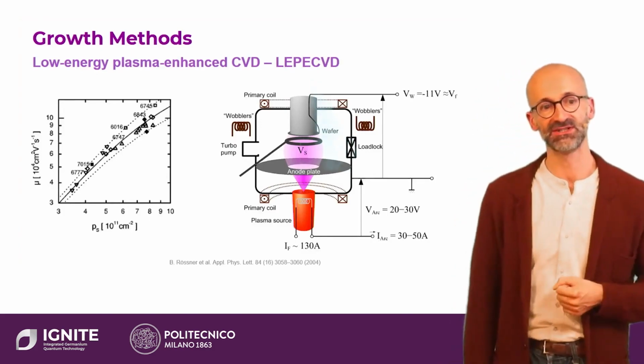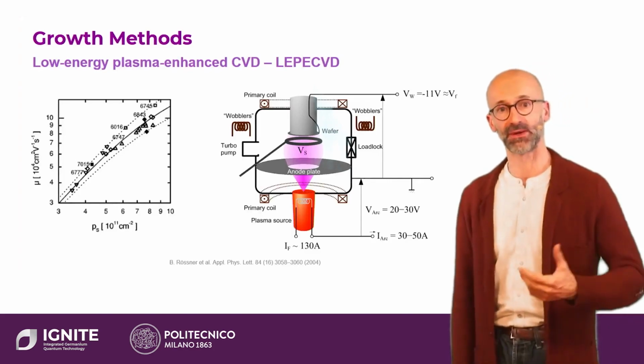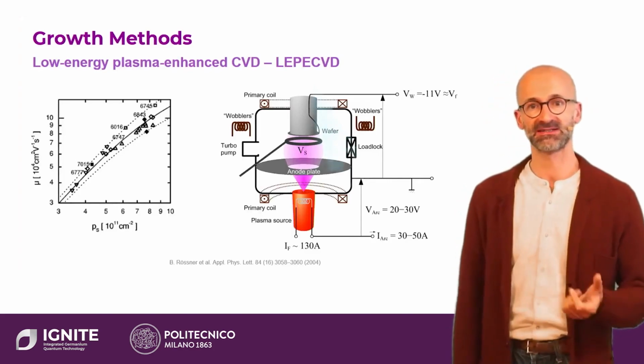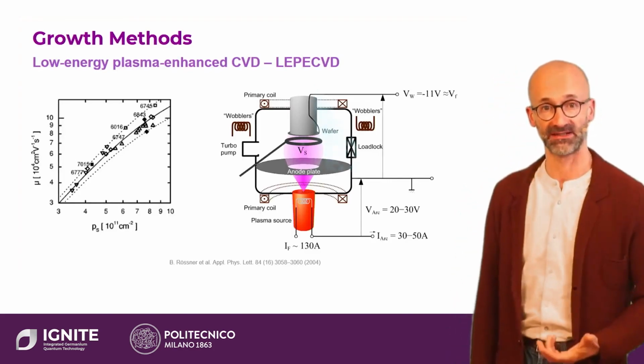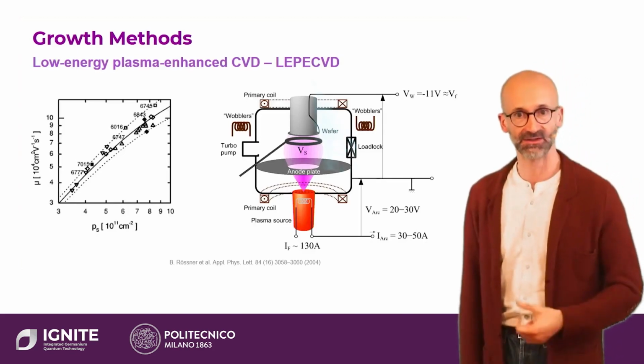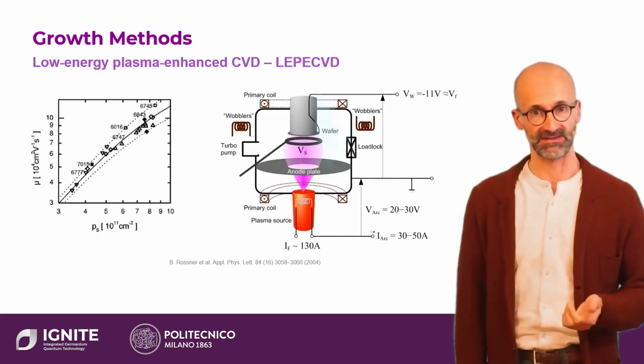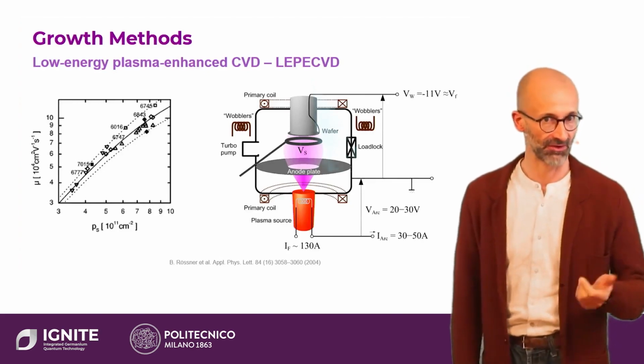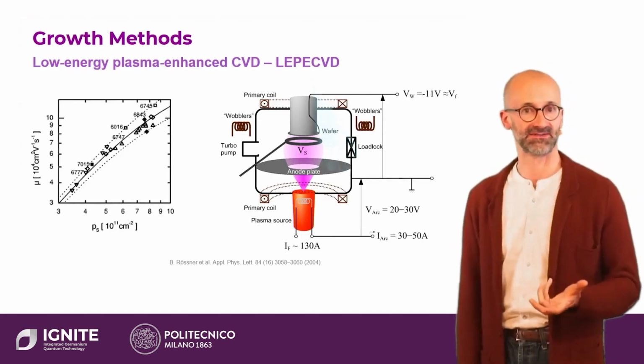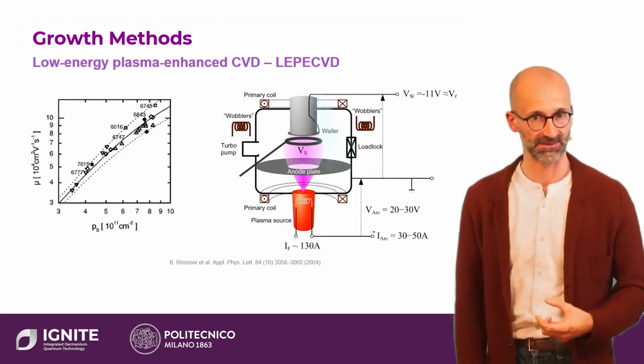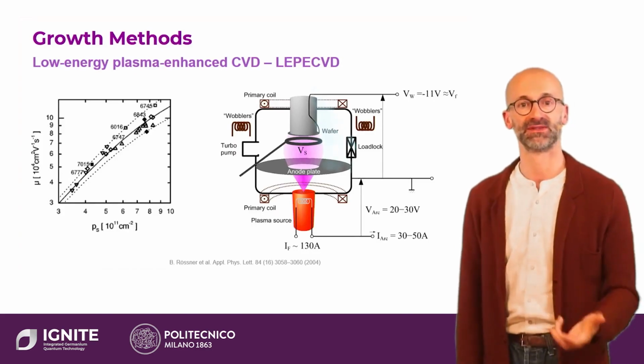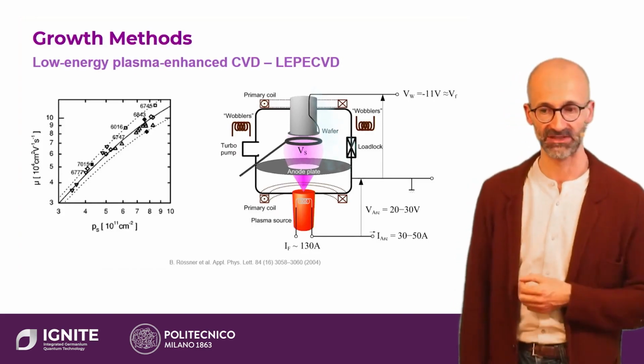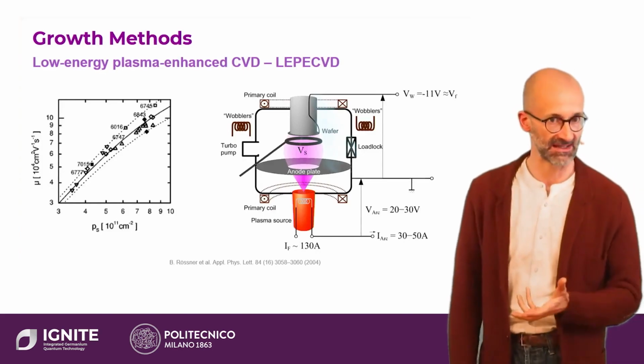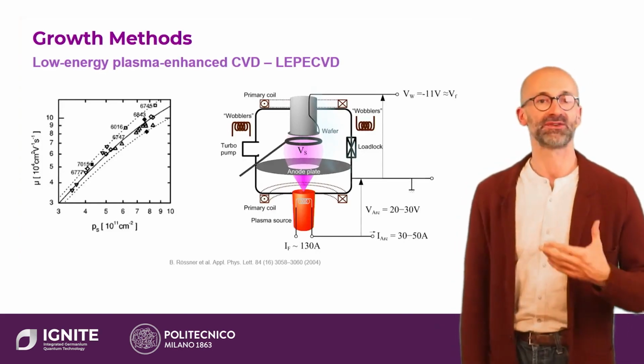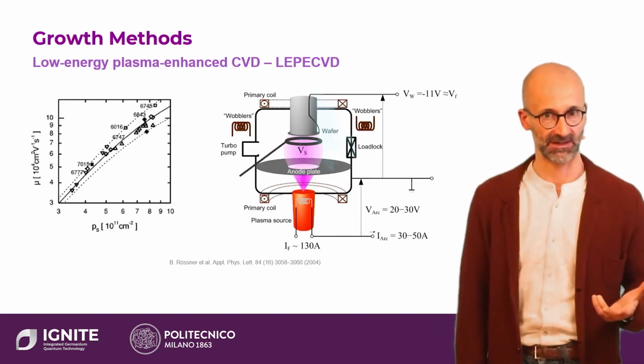The reactive conditions in the plasma, the high density of electrons, however, means that these gaseous precursors are cracked into very reactive radicals. And these neutral radicals are responsible for very high growth rates. And the growth rates are now not dependent on the substrate temperature because the chemistry is happening in the plasma. The energy is provided by the plasma, not the substrate temperature. This means that we can grow at 5 to 10 nanometers per second without any influence of the substrate temperature.